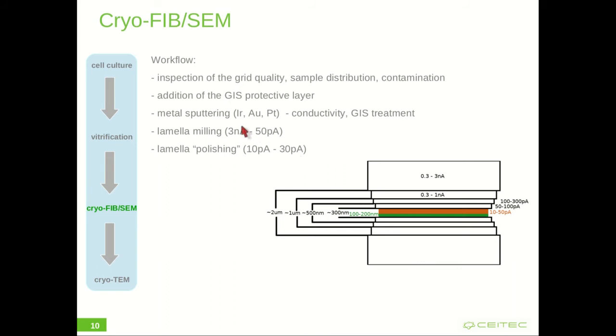First, we inspect the grid quality, check for sample distribution and surface contamination. Then the surface of the grid is coated with a protective layer of GIS. The additional metal sputtering increases the sample conductivity and cures the GIS layer. After that, we start milling the rough lamella with relatively large current and gradually decrease the lamella thickness and width, together with decreasing milling current. The final polishing step then results in a 100 to 200 nanometer thick lamella.